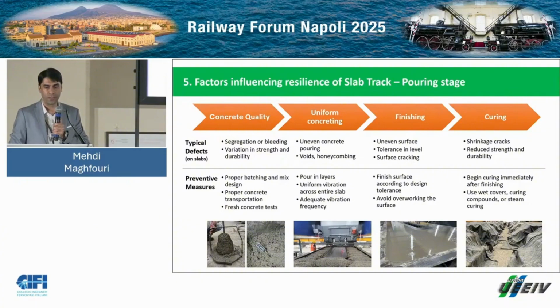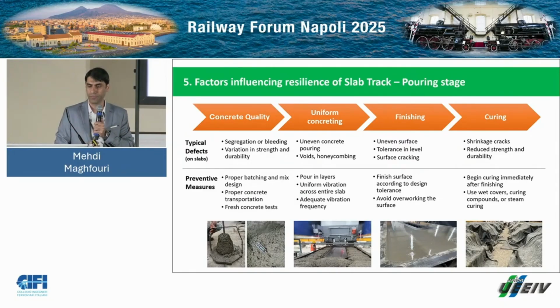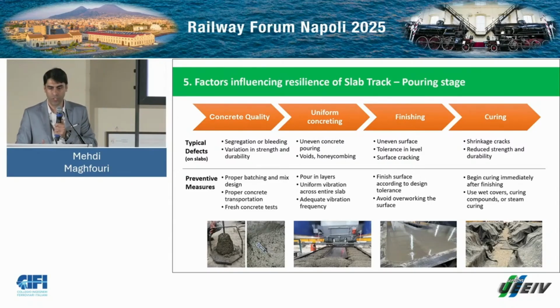Uniform concreting: uneven concrete pouring can happen, and voids or honeycombs. So the concrete shall be discharged layer by layer and then properly vibrated. The duration, everything is really important. Either pneumatic or electric mold vibration shall be used, and then, of course, the adequate vibration frequency.